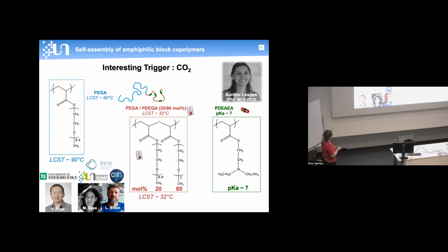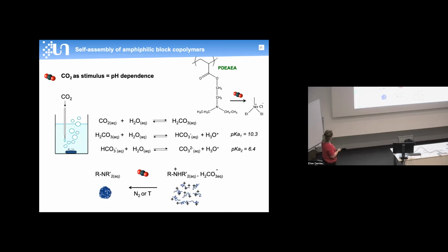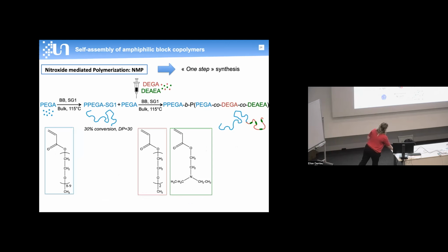but in this case, in order to tune the pH, we use an interesting trigger, as I said, which is the carbon dioxide, because when you introduce carbon dioxide in water, it forms carbonate ion and also hydronium ion that can protonate the amine function. And this is completely reversible, either by introducing nitrogen or by increasing the temperature. So this trigger is very interesting in the case of the pH, because it avoids the accumulation of salt when you add acid or base when doing cycles.